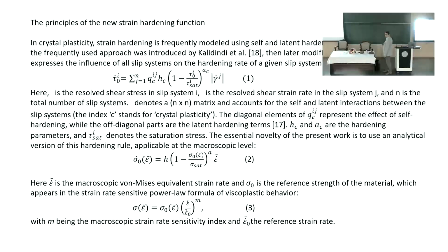It's going to be sigma, the macroscopic stress. And epsilon dot is replacing the shear rate in the slip system with the macroscopic shear rate of the sample. Similarly, we replace this tau 0 with the macroscopic stress response of the whole polycrystal. So this is the idea, this is how it comes, actually.